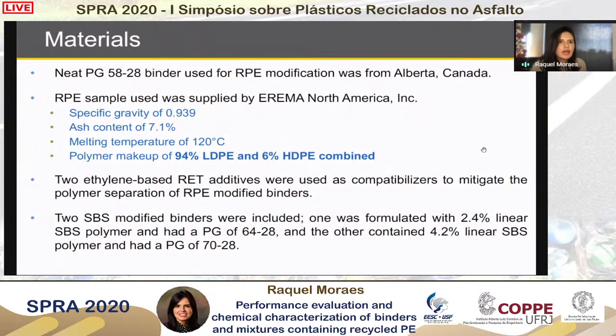That is where this recycled plastic is a blend of low-density polyethylene and high-density polyethylene combined, 94% of low-density and 6% of high-density polyethylene. Then we have two ethylene-based RET, that is a terpolymer, that were used as compatibilizers to mitigate the phase separation between the recycled plastics and the asphalt binder. And for comparative purposes, in terms of performance, we have two SBS modified binders that were included in the study. One was formulated with 2.4% linear SBS, giving us a final PG of 64-28. And the second one contains 4.2% of linear SBS polymer with a final PG of 70-28.